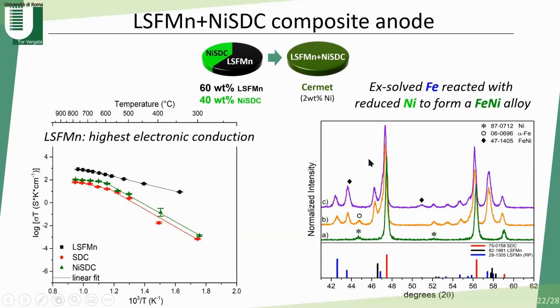Here I reported the XRD of the compounds of the anode compared to the single components. What we can see is that in the composite anode we have the presence of iron-nickel alloy. So the iron exsolved from the perovskite and the nickel from the electrocatalyst form an alloy that can mitigate the carbon deposition.